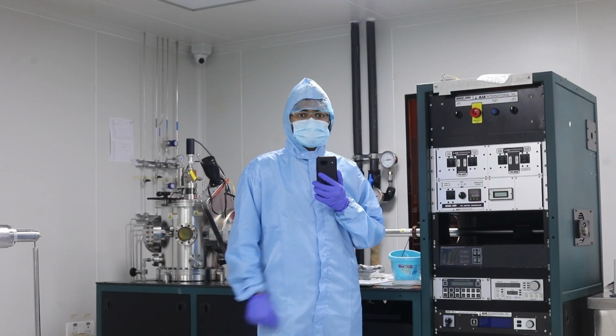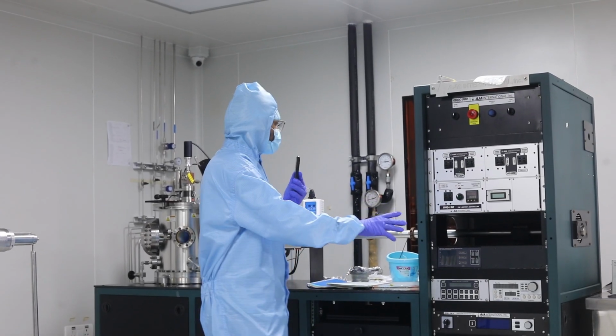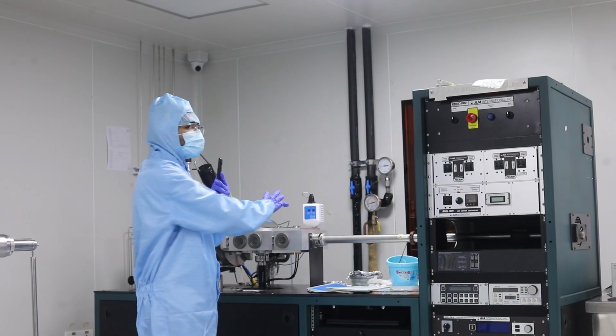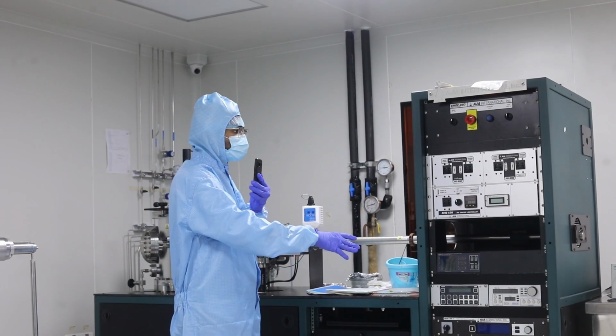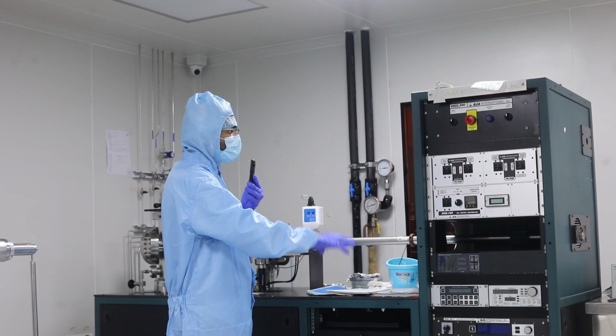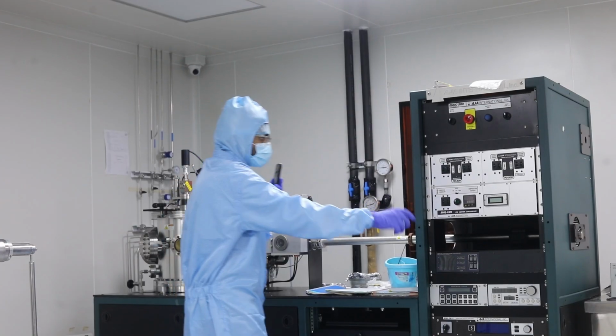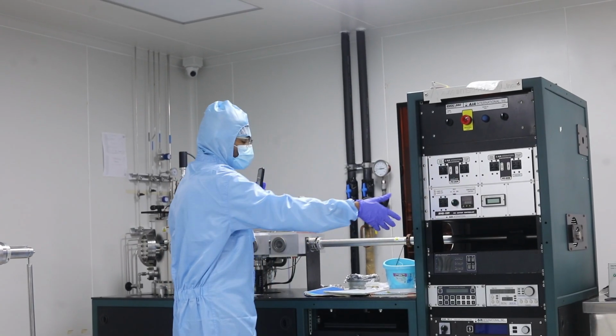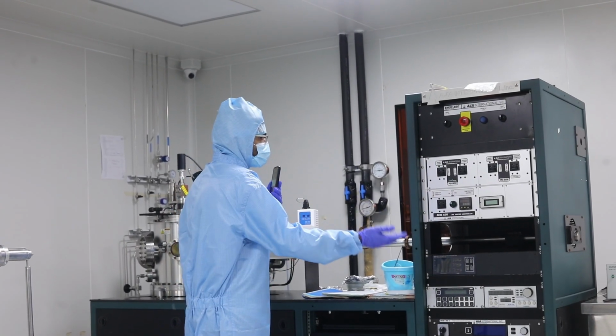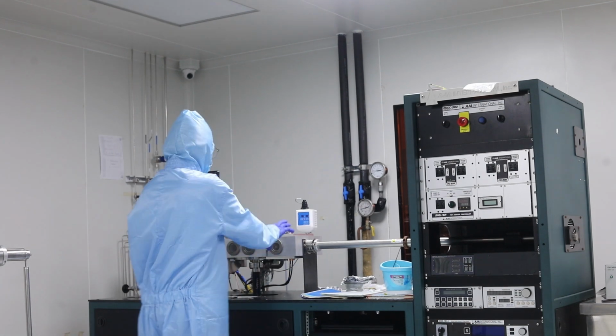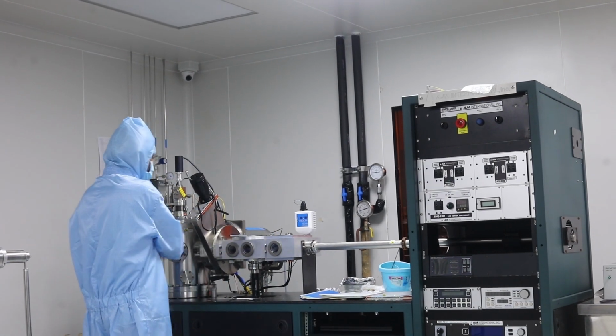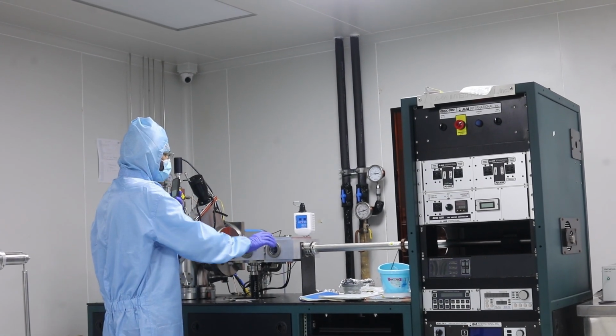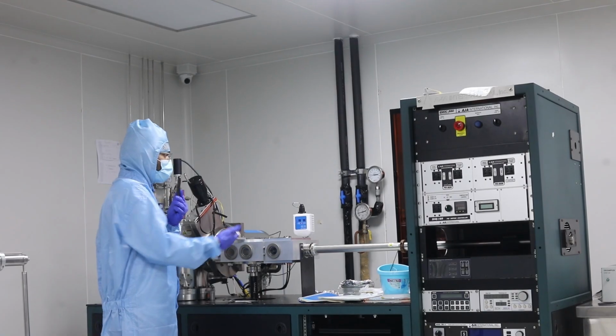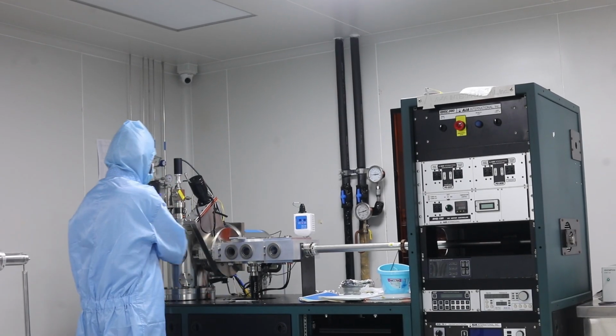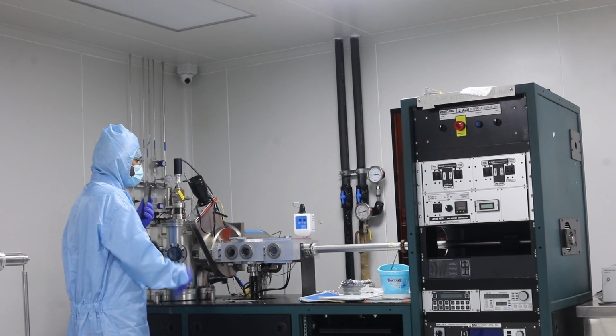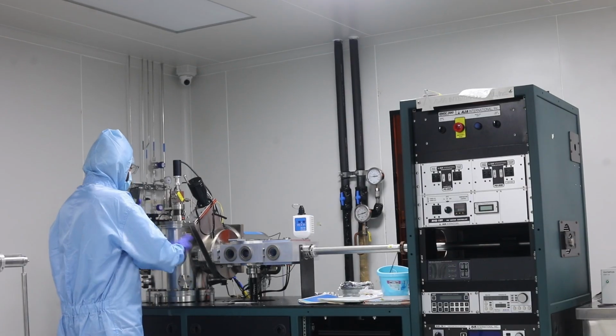Now we are in front of the sputtering machine. Here we can see there are two different parts of the system. Here we can control the pressures and other parameters of the machine. We have a magnetron magnet here which we can use during the loading of the substrate. Here we can see a load lock chamber and a main chamber. The load lock chamber works at a pressure of around 10 power minus 3 to 10 power minus 4 bar, and the main chamber works at 10 power minus 9 torr.